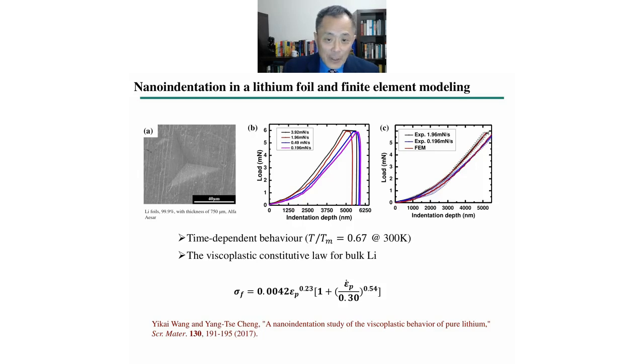Indeed, using nanoindentation with a Berkovich indenter, we found that the loading rate has an effect. Specifically, at a higher loading rate, in order to push the indenter to the same depth, one has to use greater force. By combining nanoindentation with finite element modeling, we proposed a constitutive relationship for metallic lithium at room temperature. The strength of lithium is indeed both strain and strain rate sensitive.